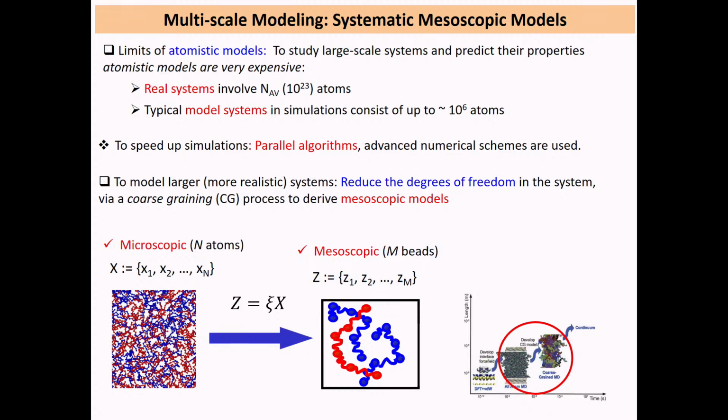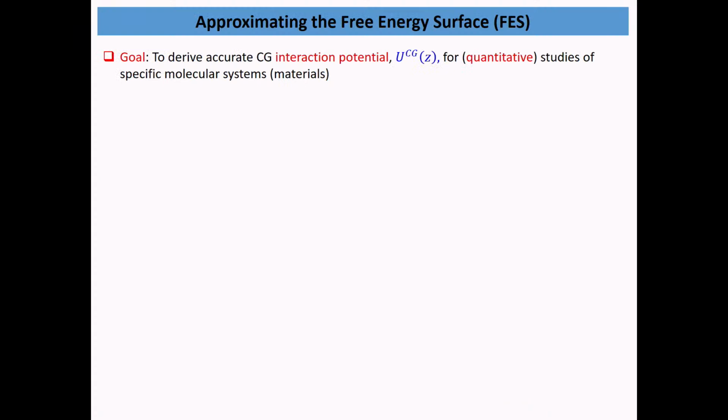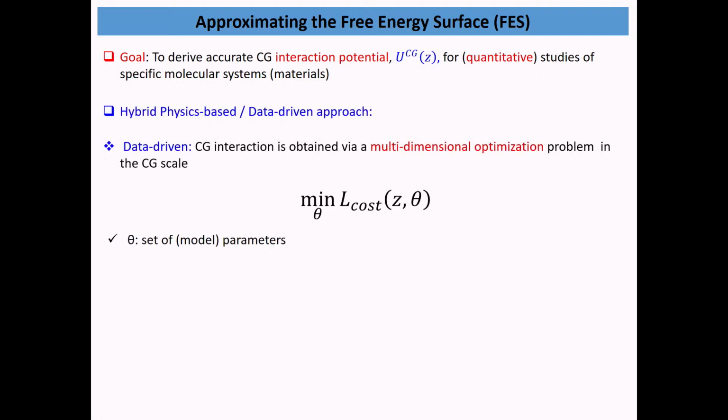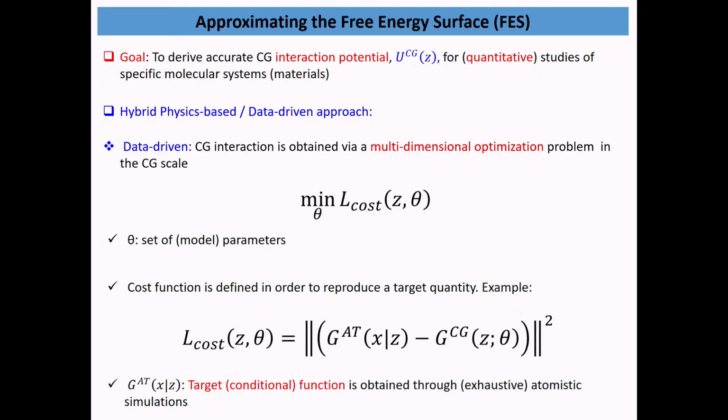Okay, so these are called typically mesoscopic or coarse-grained models. Again, the challenge here is to derive another interaction potential because it's in a different scale. So it's not anymore an atom scale. And again, the standard way to solve this is by trying to solve an inverse problem. It's standard, but it's not easy quite often. So again, we define a minimization, a cost function, and the goal is to minimize that. There are many techniques. I will not say anything about that.